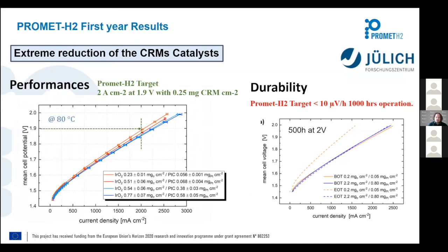Next, I would like to show the work that was developed by Jülich. In this case, Jülich wanted to work on the active layer, and they developed some techniques to try to reduce as much as they can the load of the iridium oxide. In the left side graph, you can see how low loadings can work and can achieve a really good performance. We even achieved the target from PROMET H2 regarding the loading.